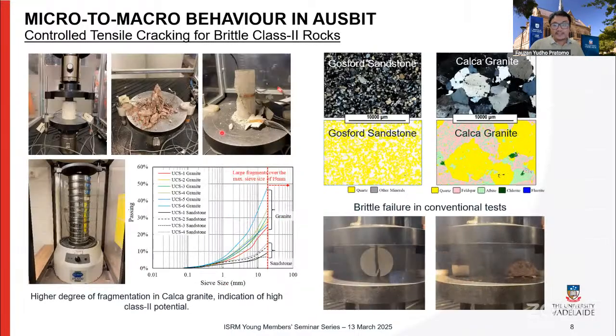So from sieve analysis after the UCS test, we can see how much more fragmented the granite is, which is a strong indication of class 2 based on past research. And this was a product of the violent bursting failure. The sandstone here showed brittle failure, but not too violent. It consists of fine quartz as the main composition, while the granite was dominantly large quartz and feldspar grains.